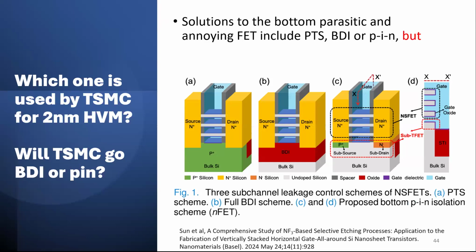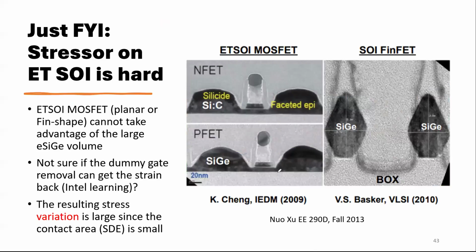Because when you grow epi from a lot of silicon, it's much better than growing from no or thin silicon. The reason is this. If you grow epi, say 1 nanometer, will that work? It will never work, because 1 nanometer is highly strained.